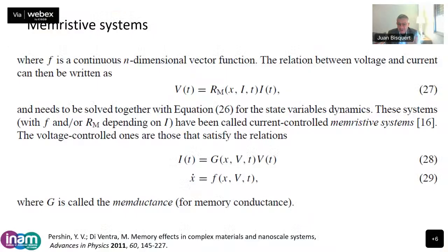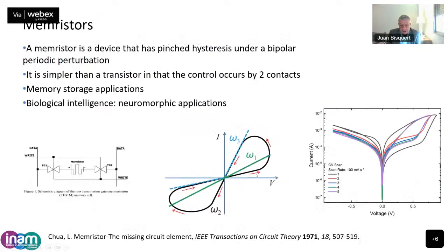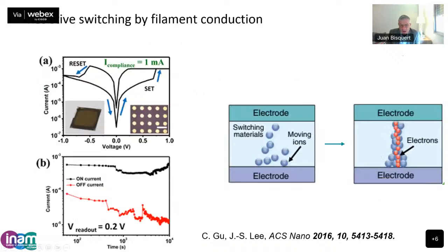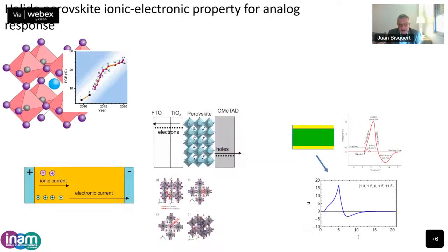perovskites we can make memristors. Memristors have this big memory effect with the equation, which is the same as the chemical inductor I said before. And with halide perovskite we can make memristors, and the memristor you can see now that is a system that has a very big pinched hysteresis, so that with this you can do two conduction states, less conduction or more conduction, related to the